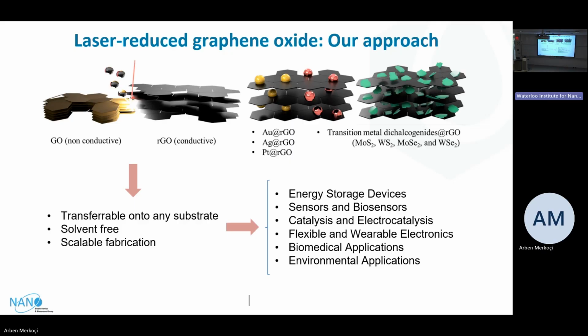So we start from graphene oxide, which is not conductive, to reduce graphene oxide, and afterwards using even some precursors of metallic particles, and even some transition metal dichalcogenides, we are able to produce different kinds of substrates with different configurations, composites, mixtures of graphene with different kinds of nanomaterials, with interest for different applications, because we are trying to get synergies between graphene or other 2D materials with nanomaterials, so as to anchor, for example, receptors, or to use these for energy applications.